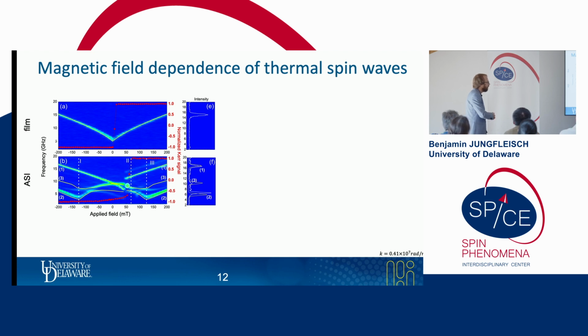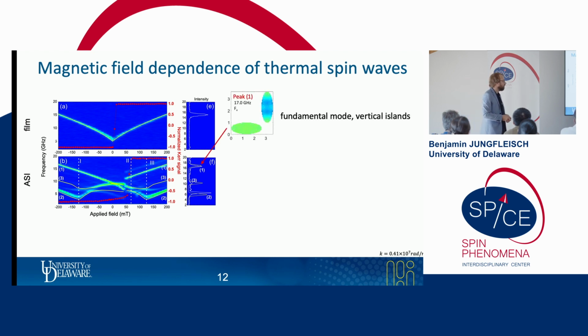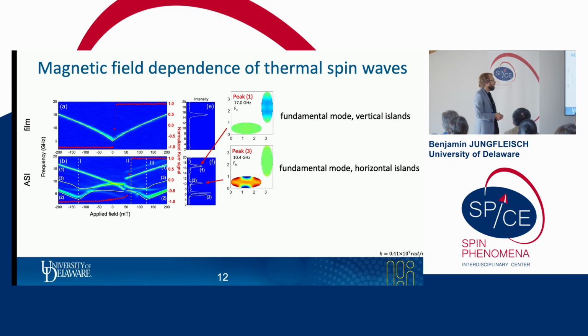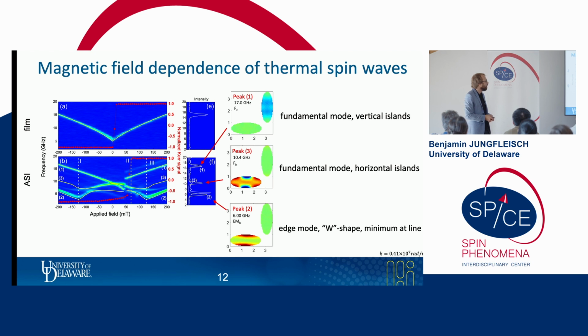And this correlates with this mode switching of peak number 1. So this is associated with the vertical elements. Now we see here 3 modes. Let's take a closer look at what those modes are. Peak 1 is the fundamental mode of the vertical elements. Peak 3 here is the fundamental mode of the horizontal islands. And peak 2 down there is the edge mode. This gives rise to this characteristic W shape that we see over here, with the minimum frequency at these vertical lines 1 and 3.